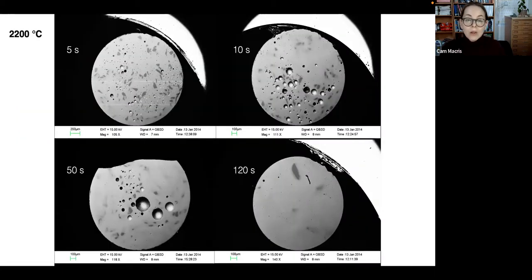What I'm showing here are some more backscattered electron images of cross sections of these glass spheres after an experiment. So these were heated to 2200 degrees Celsius for varying times. And there's a clear textural evolution with time. So if we start by looking at this one, which was heated for 5 seconds, some of the quartz grains, which are the darker brown, darker gray blebs, are still in the process of converting to Le Chatelierite. So we still have some crystalline quartz here. At 10 seconds, we have complete conversion from quartz to Le Chatelierite. We're also developing more and larger vesicles. By 50 seconds, we've reproduced the Schlieren that we saw in the natural sample. And in the longest experiment, we're nearly vesicle free, and we have significantly fewer Le Chatelierite.